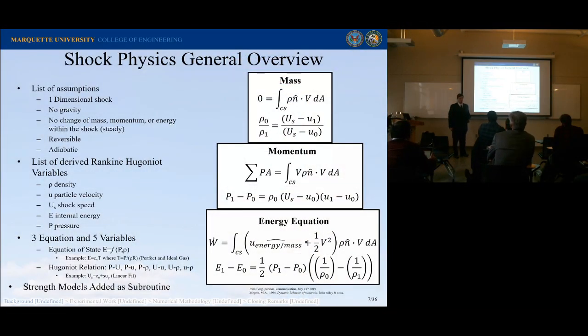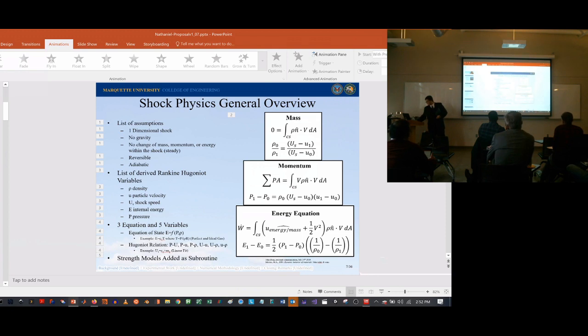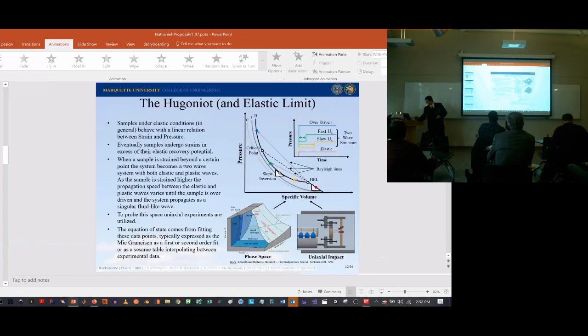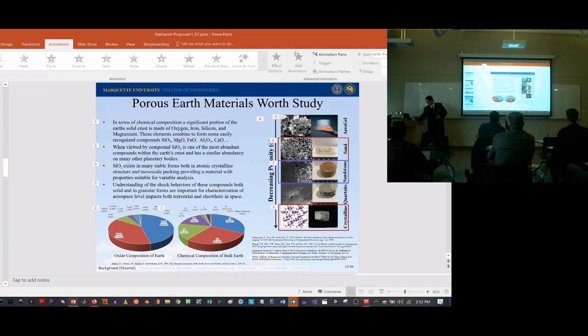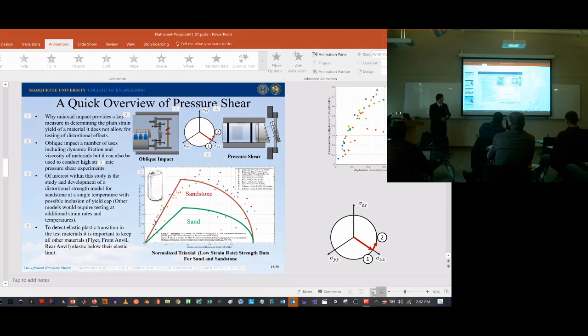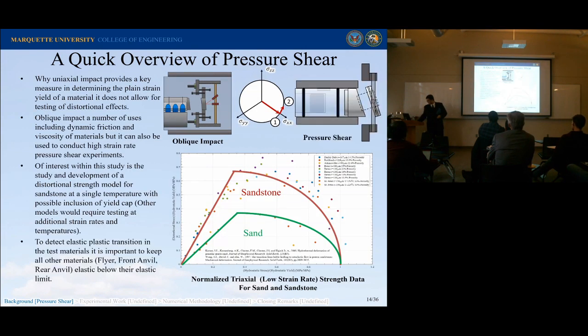So those 2 items. You showed those strengths up there that are measured, so how is what you're proposing to do different from what's been done? If you're referring to this graph right here, this is normalized triaxial tests, and this is at low strain rate. The reason why my study is important, the reason that Jeff's study was important, is we're doing it at a different strain rate. If you recall one of the diagrams in the upper right-hand corner, you could see that strain rate had a large effect on strength. So the way you figure that out is to measure it empirically.